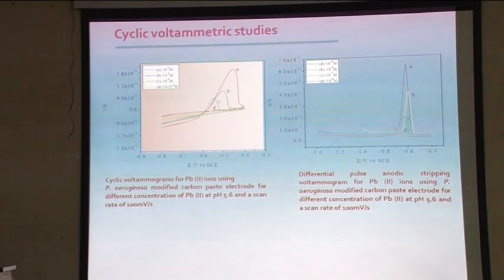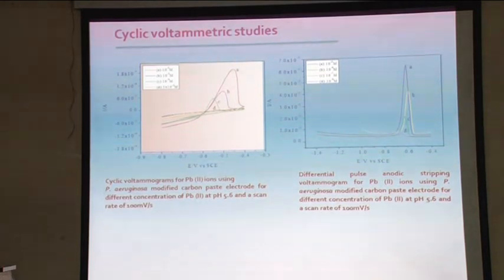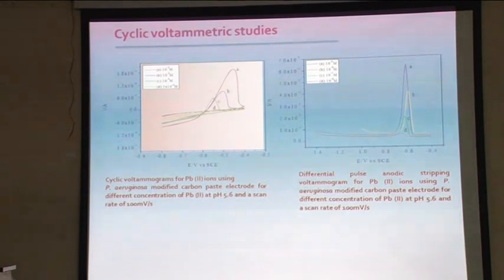And once you use the differential pulse anodic stripping voltammetry, you can go to still lower concentrations. So this is something that we have done where you can actually do the capture of the metal ions from the effluent, which is actually taken as the electrolyte, onto the cells, onto the electrode surface, which is a modified biomass loaded carbon based electrode.